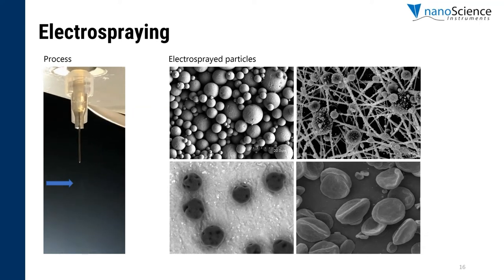If you look really carefully at the blue arrow, you will be able to see that electrospraying in action. It's really hard to see, but this is how the electrospraying process is happening. We also have a few examples in this slide of electrosprayed particles. By using different polymer and solvent combinations, along with sample processing parameters, you can get different morphology features, from well-rounded particles to rough ones to collapsed shapes, and even particles that can be sprayed simultaneously through the electrospraying technique.